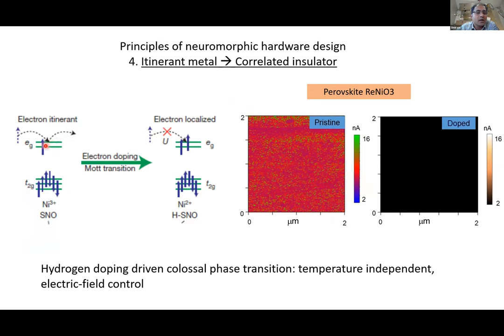So if you start with the electronic configuration of a nickelate, which has one eg electron, and then add one more electron from an electron donor like hydrogen, you can have what's called half filling, and then this results in a massive phase transition. So you can see this is the conducting AFM of a pristine compound. When you add electrons, it becomes nearly fully insulating. So you have this nearly 10 to the 8, 10 to the 10 orders of magnitude change in conductivity arising from electron doping. And this is independent of temperature. And you can also control this by electric fields or external stimuli, because the hydrogen is charged and so it responds to electric fields.